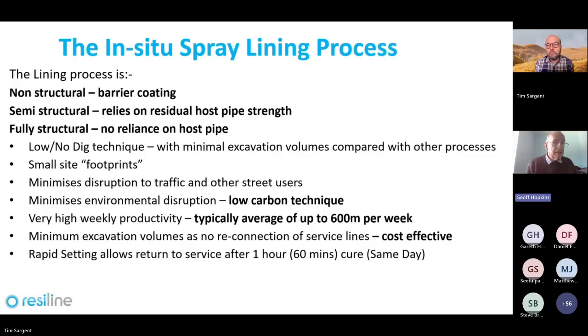Thank you. So a little bit more about the process. These days we can use the process still as a non-structural barrier coating to clean out internal incrustation and degradation in the pipe, and apply a sealing coat as a thin non-structural lining. A semi-structural lining relies on the residual host pipe strength, but basically the lining is thicker and it can act as a clamped plate over holes and defects that appear through the pipe wall. So quite useful for what are termed partially deteriorated pipes. And it's possible to install fully structural pipes, which effectively can be considered standalone pipes that don't rely on the old host pipe in any way.